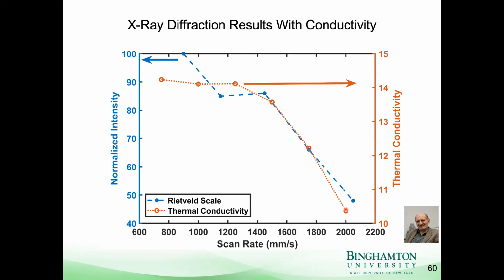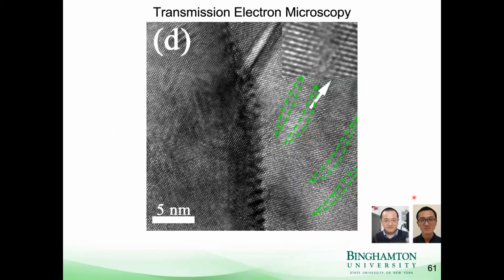And we next did transmission electron microscopy. My colleague Guangwen Zhou and Xiaobo did transmission electron microscopy on this sample. Here's the interface between two grains. This is high resolution TEM, so the scale bar here is just 5 nanometers, incredibly small. And if we zoom in here inside the stainless steel, you can see regions that are somewhat blurry. This is actually indicating that there's some amorphous region inside the stainless steel. And we think that this amorphous region is leading to a reduction in X-ray diffraction intensity and also reducing the thermal conductivity of the stainless steel at those faster scan rates.